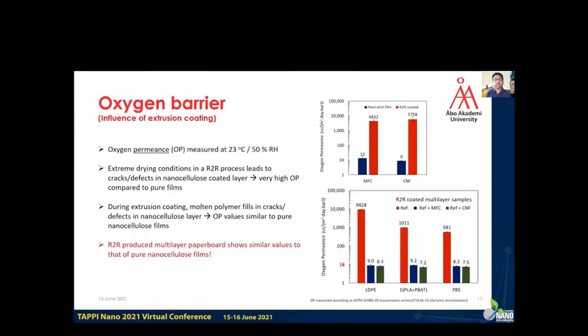Moving on to oxygen barrier, here we look at the influence of extrusion coating polymers, and the oxygen permeance was measured at 23 degrees Celsius and 50% relative humidity. Let us first start with the image on the top. Here we have a comparison of Petri dish films versus roll-to-roll coated nanocellulose samples. Compared to Petri dish films, we can see the roll-to-roll coated films have a very high oxygen permeance. One thing to note is that this is a logarithmic scale, so it actually has 3 orders of magnitude higher permeance.